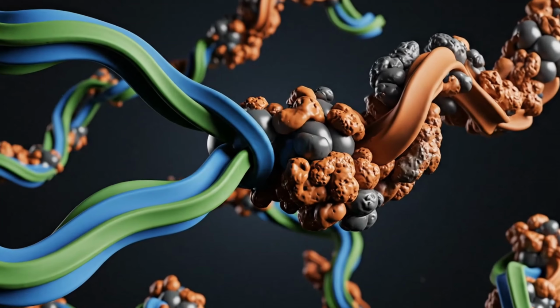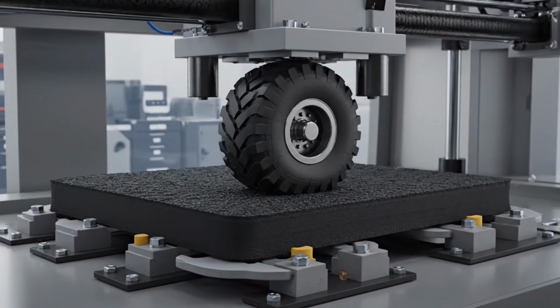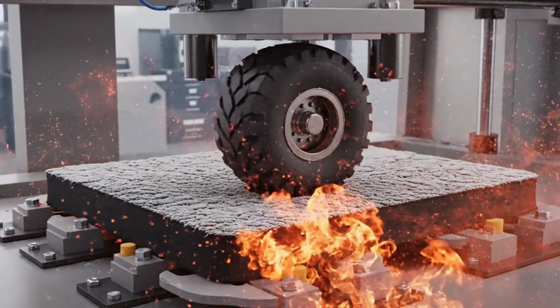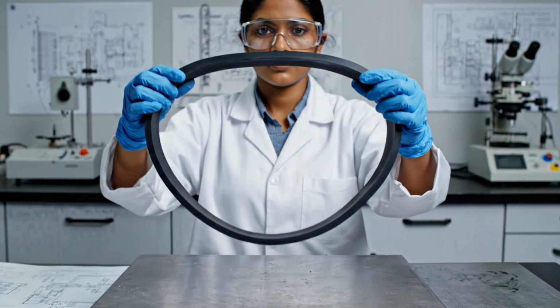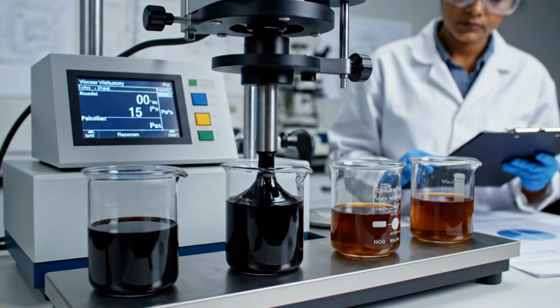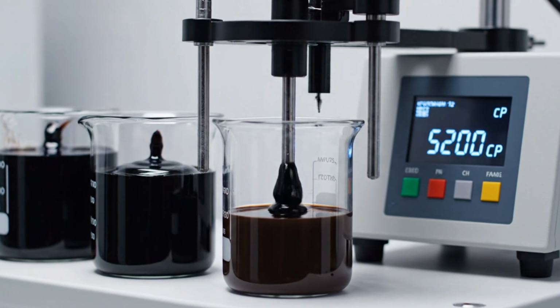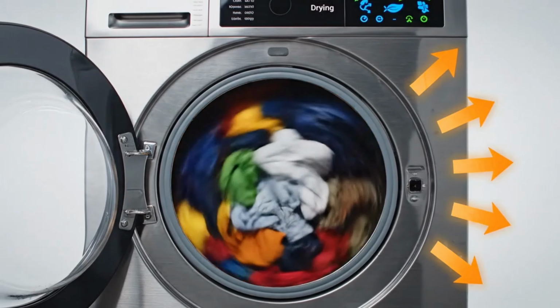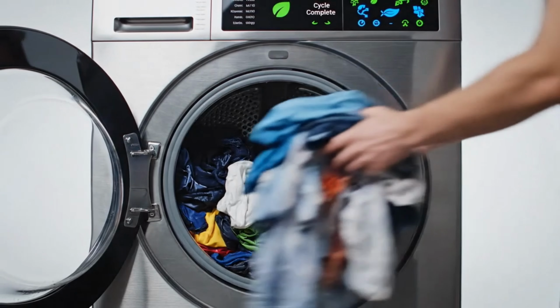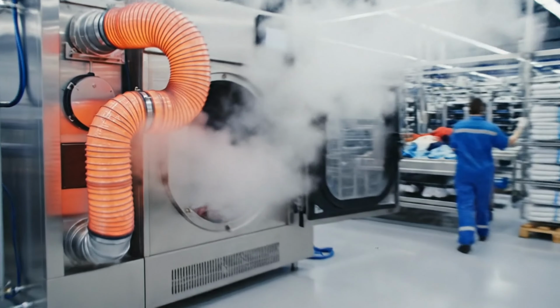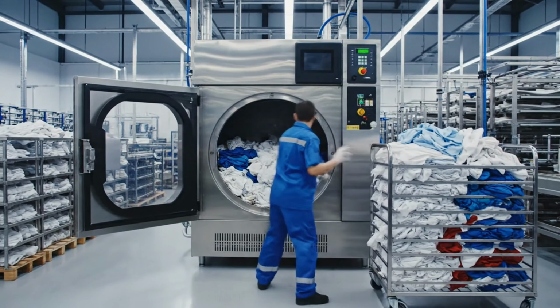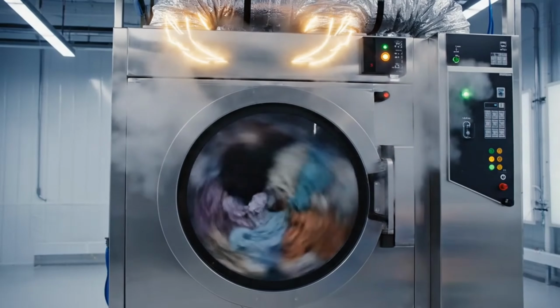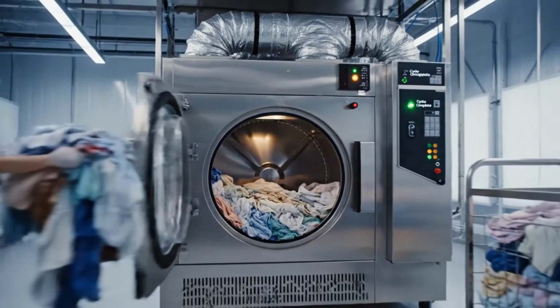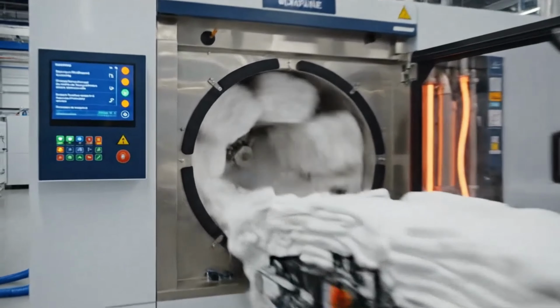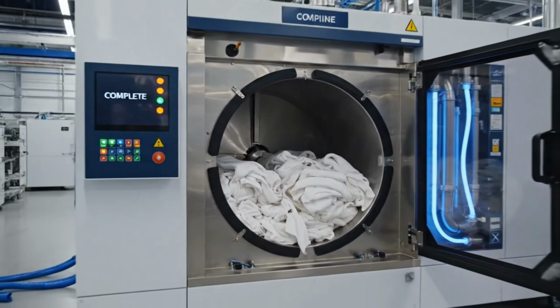Workers feed tires into specialized bead removal machines. Inside, a hydraulic hook system capable of generating enormous pulling force digs deep into the tire bead. Using brute mechanical strength, it extracts the entire steel core in just seconds. The force is so intense that the thick rubber body violently twists and deforms during the process. Each heavy-duty truck tire yields around 2 kilograms of high-quality carbon steel. Once separated, these steel wires are compressed into compact bundles and transported to metallurgical plants, where they begin a completely new life cycle. Meanwhile, the remaining tire carcass, now far more flexible, is ready for the next stage.